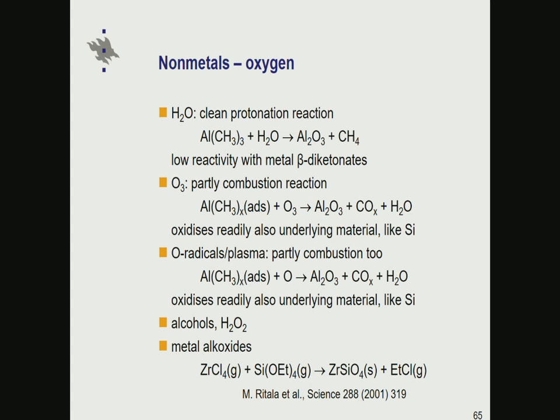Oxides have been dominating in ALD of compounds, and as a result I start from oxygen precursors. Most of the ALD oxide research has been done using one of these three: either water, ozone, or oxygen radicals, or oxygen plasma. Water is nice in the sense that for those metal precursors which react with water, one can consider these reactions pretty clean, so that the ligand is removed from the metal by simply and nicely protonating. As a result, the ligand stays intact. There's a transfer of hydrogen from the water to this ligand. It forms methane in this case, and it goes away.